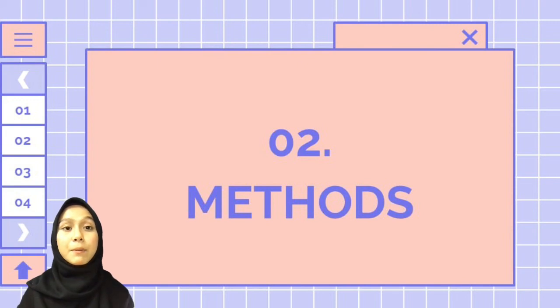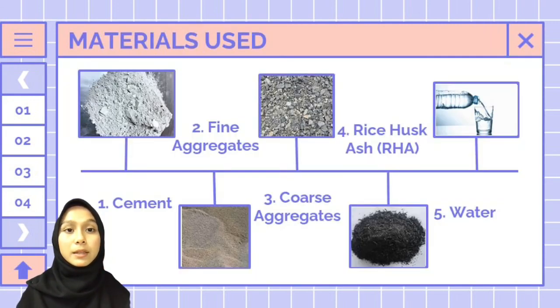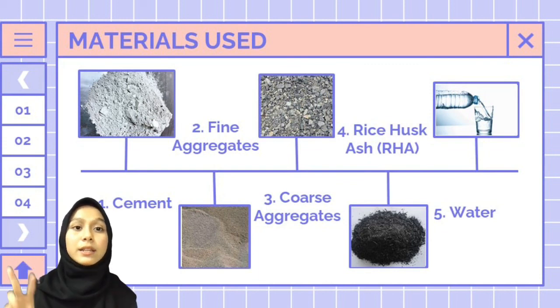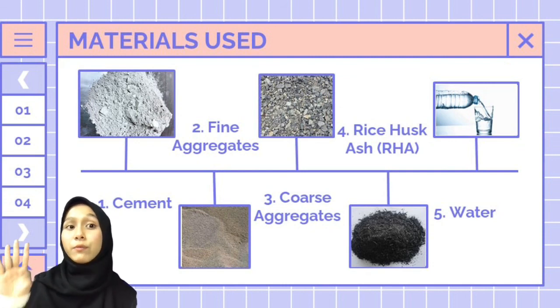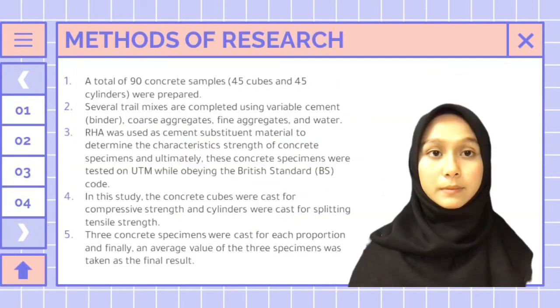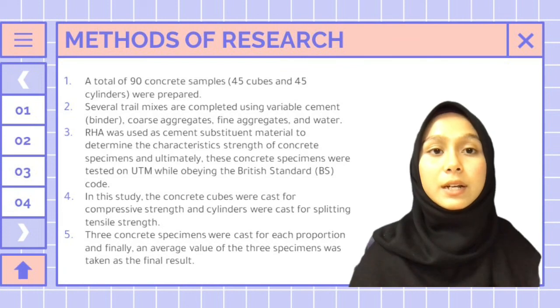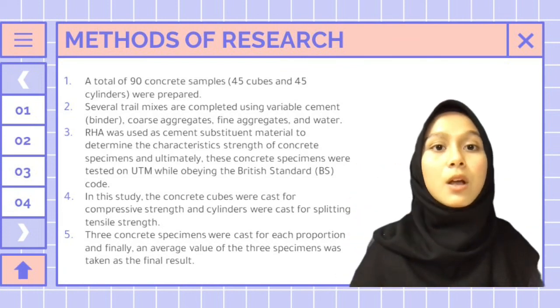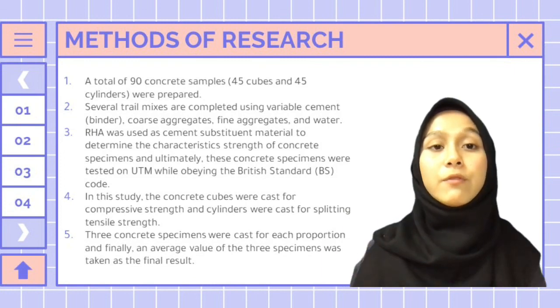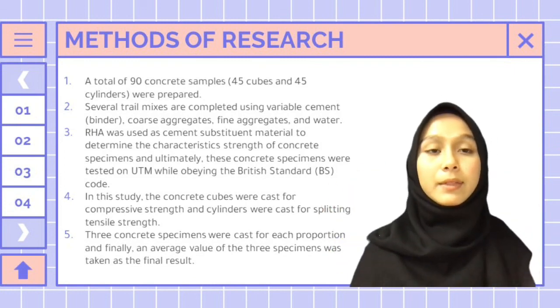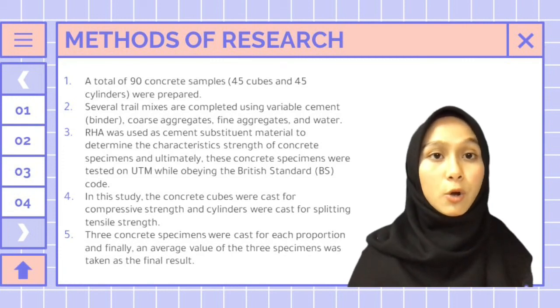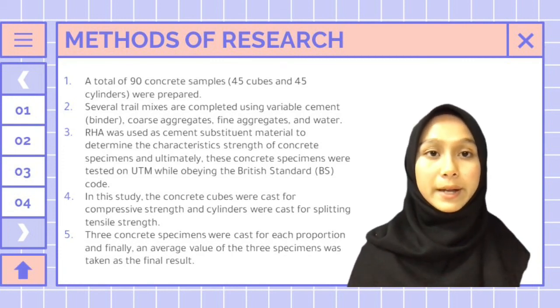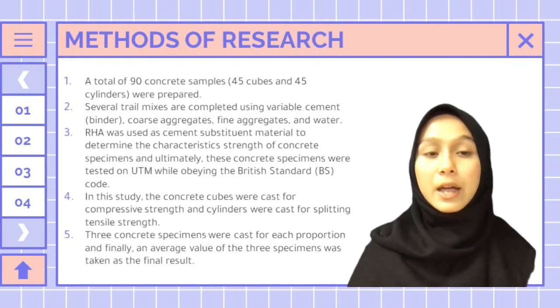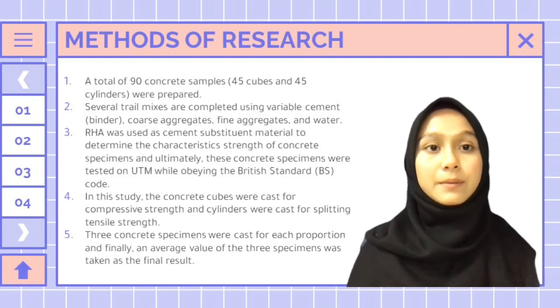Secondly, I will explain about the method used in this research. The materials in this experiment: the first one is cement, the second one is fine aggregate, the third one is coarse aggregate, the fourth one is rice husk ash, which is RHA, and the fifth one is water. The tests were done with a total of 90 concrete samples, 45 cube samples and 45 cylinder samples were prepared. Next, several trial mixes are done using variable cement or binder, coarse aggregate, fine aggregate and water to get the optimum mix.